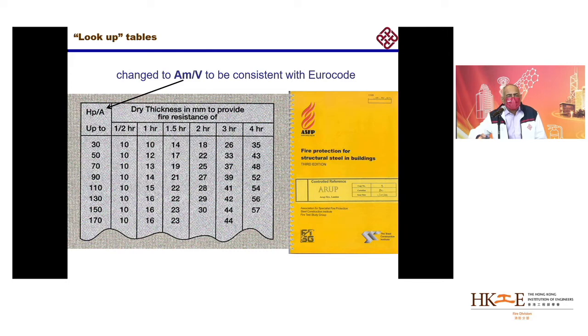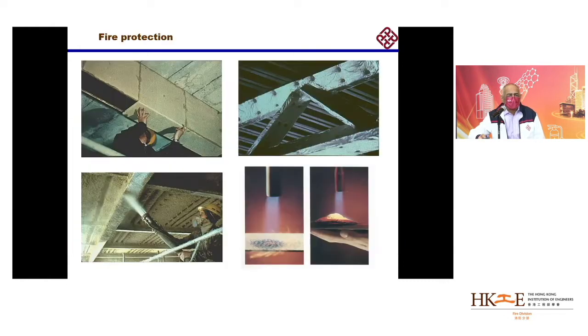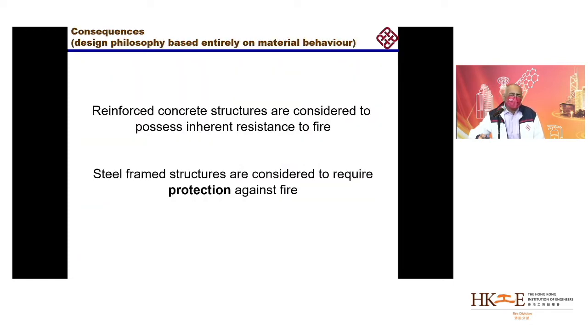Then you can go into tables and look at the surface area to volume ratio, and look at the requirement from the code of how many hours you want the protection for, whether half an hour, 1 hour, or more, and then you can get the dry thickness in millimeters for the insulation thickness that you need to apply to achieve that protection. These are the different options you have, like board, spray, intumescent paints and blanket. So this is basically what generally happens, and it's been happening in this way for a long time.